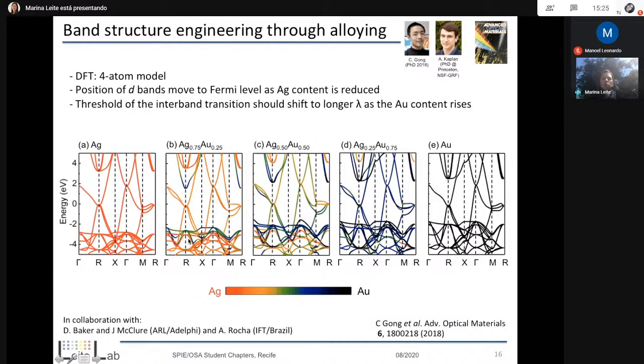And another thing that we could realize, thanks to the DFT, is that there was a threshold for an interband transition. So we're very interested in the gamma point here. If you think back to your solid state classes, right, the distance between these two. We're very interested in seeing how much these interband transitions shift to longer wavelength with increasing gold content. So basically what I'm telling you is that this gap here decreases with the increase of gold content. That's essentially what I'm telling you.